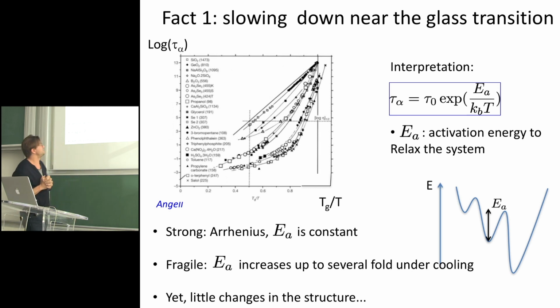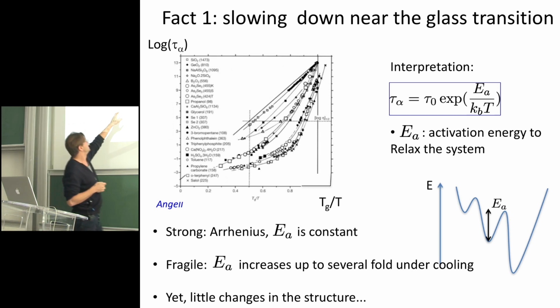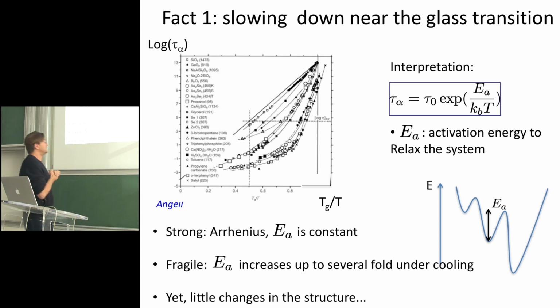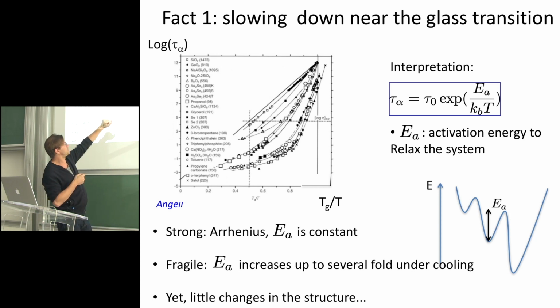Okay, so one way to think about what's going on is that there are barriers that particles need to move around in the system to relax. And so you can think about this relaxation time as some microscopic time scale times the exponential of those barriers divided by kT. And in some liquids that are called strong, actually this activation energy EA is constant, like silicate.